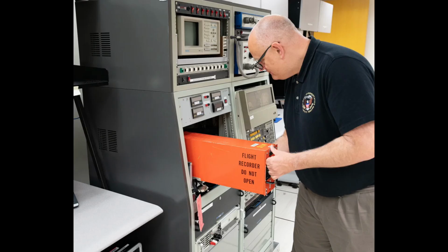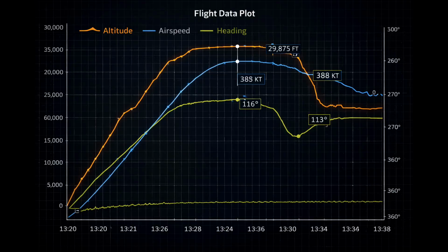Crack growth accelerates from millimeters per cycle to meters per second. The fuselage skin, once a continuous pressure boundary, ruptures explosively. Cabin air expands outward at near sonic velocity, tearing insulation, flooring, and wiring from their mounts. The pressure differential does not dissipate gently, it equalizes violently. Structural frames experience asymmetric loading. Loads shift faster than control systems can react. The aircraft does not break. It is unzipped by physics.